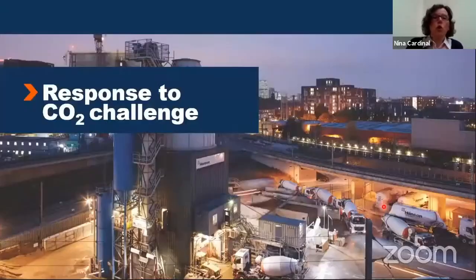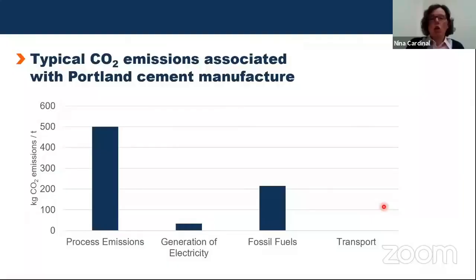So first of all, what is our challenge and the response to it? On this slide, on the y-axis, are the CO2 emissions per ton of cement produced. That is traditional Portland cement. As you can see, about 2/3 of the CO2 emissions are associated with the process itself. This comes from the calcination of limestone to lime. By the laws of physics, we release CO2 in this process and cannot change it.